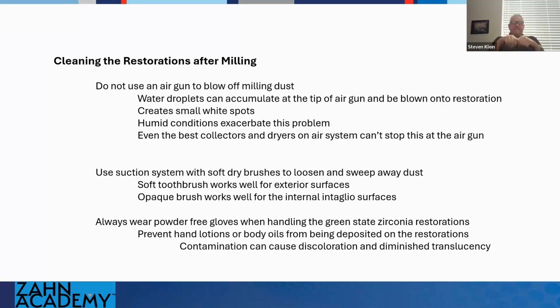The other thing that I run into quite frequently on technical troubleshooting would be spots or discoloration on the zirconia. And a lot of that comes from either hand lotion or body oils that are deposited on the restoration prior to sintering. Now, while we see the moisture aspect of it build up during the summertime, the hand lotion and body oils typically are in the winter because it's drier air. You've got furnaces running in a lot of locations across the country. So you're lotioning up the hands and keeping your skin moisturized. But what you're doing, if you're not wearing gloves, is getting that contamination right into the zirconia, and it doesn't come out. You cannot get rid of it.